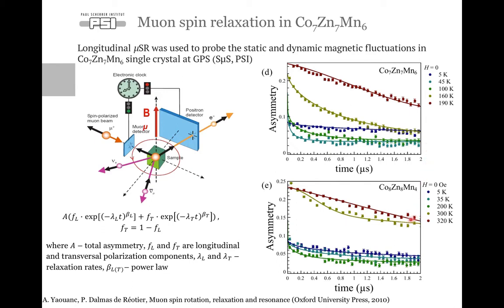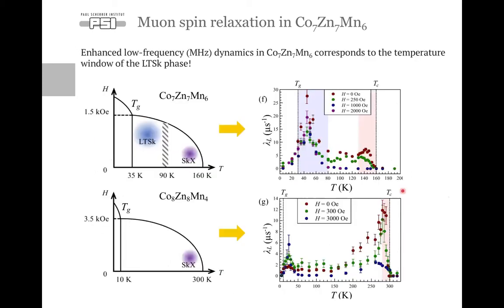And a similar picture is also observed for the 884 material, but quantitatively the characteristic relaxation times for this higher ordering temperature crystal are quite different. I will show you this in the next slide. So here I show you both phase diagrams for 776 and 884 materials. And the important reminder is that 776 has two different Skyrmion phases. One is just below TC and one is just above the spin glass transition temperature. Both of them appear in the finite magnetic field. But for the 884 material, we only have the thermal equilibrium Skyrmion phase below the paramagnetic to helimagnetic transition.